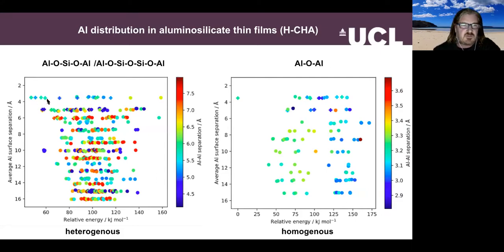These crosses here denote that water has been formed by the charge compensating proton combining with a silanol group, an SiOH species on the surface, and it's that liberation of water which gives rise to a strong driving force. I've partitioned the data into these different types of sequences, which if you remember, I asked you to keep in mind a few slides back. So these are the types of sequences that we would expect, and it turns out that if we compare the interior of the structure and towards the surface, it's more favorable to push the aluminium towards the surface in these types of sequences.